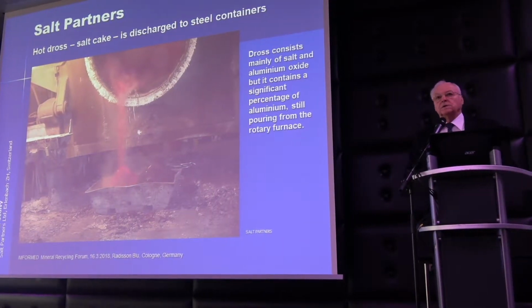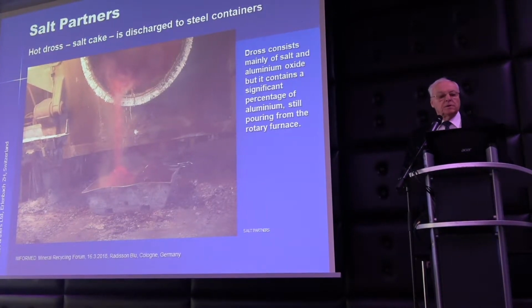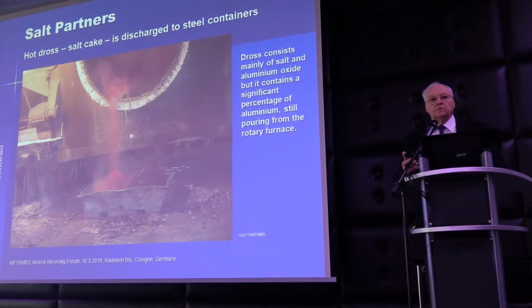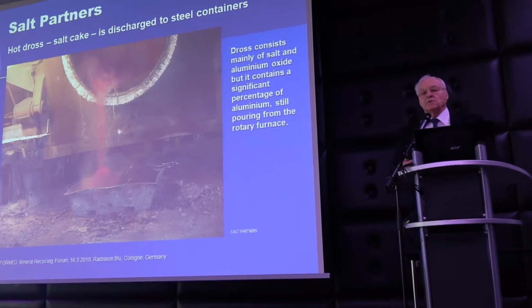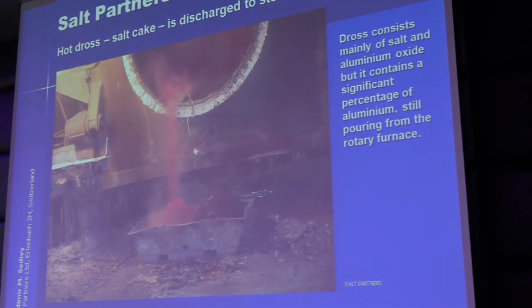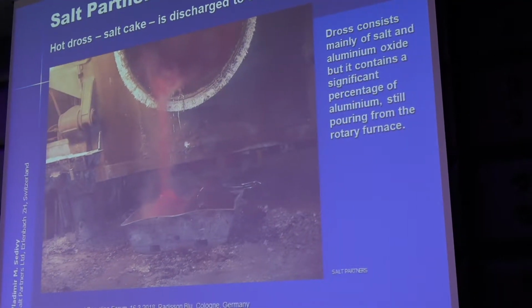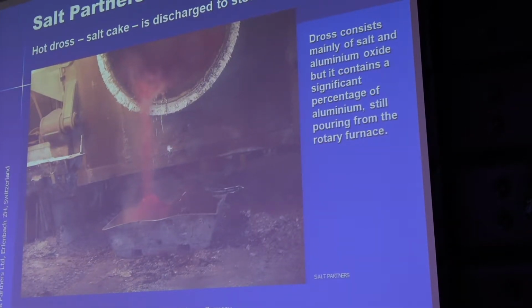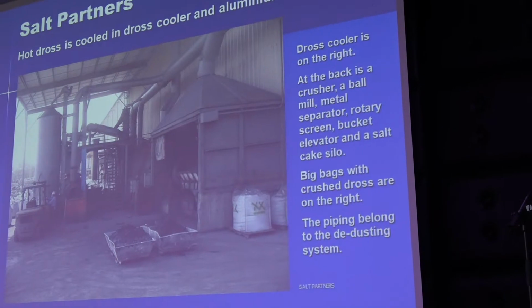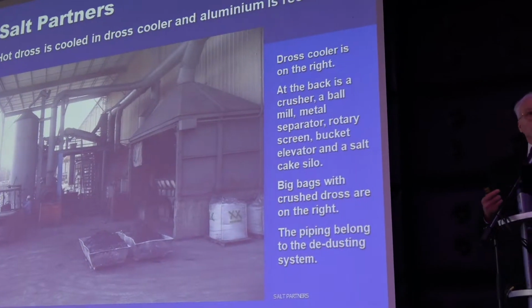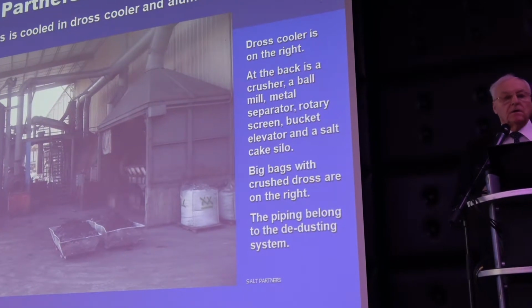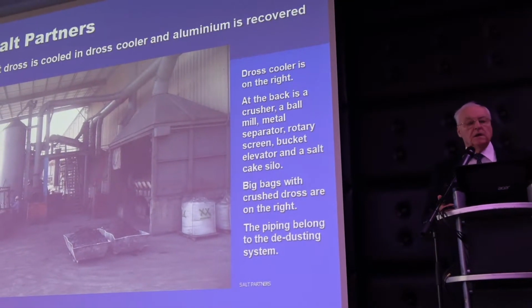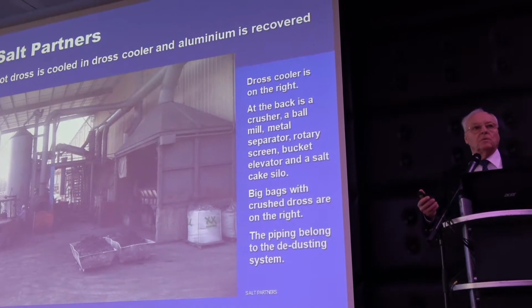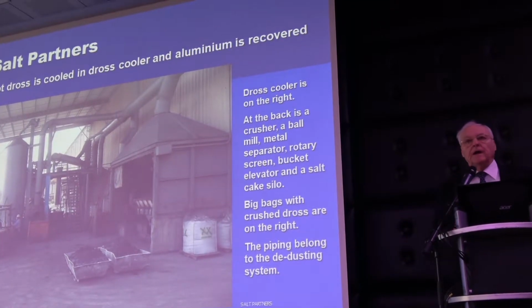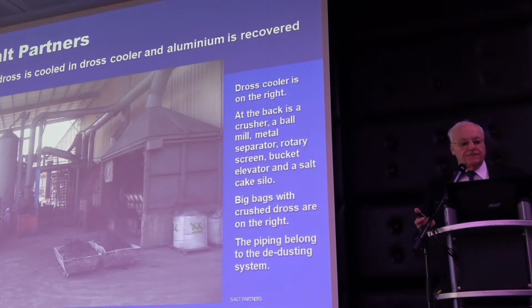After the aluminium is poured out, as much of it as possible, the hot aluminium oxides, or the dross, is removed. And as you can see here, there is still some aluminium in the dross. So what is then done with it is that the dross is thrown into a cooler. It is then crushed and screened. The larger pieces of aluminium are removed and recycled, and then the dross is left.